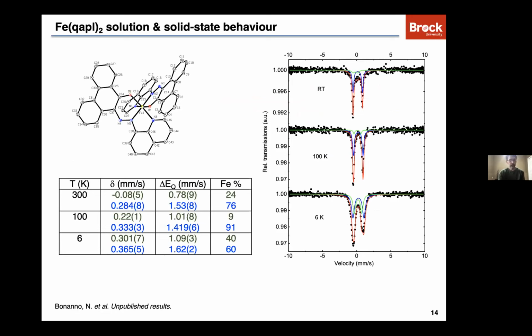which we see reflected in the proton NMR behavior in solution. We also see in the solid state two iron sites in the Mossbauer spectra, which again have Mossbauer parameters that suggest two different oxidation states of the metal. So our working hypothesis here is that we have valence tautomerism with this QAPL ligand, as I mentioned, low spin iron 2, QAPL anion going to low spin iron 3 with one anion and one dianion radical. But this is still something that we are studying, trying to iron out the details of the system.